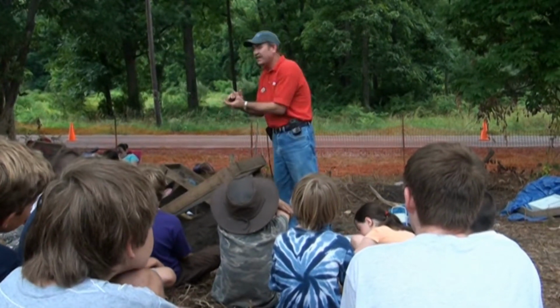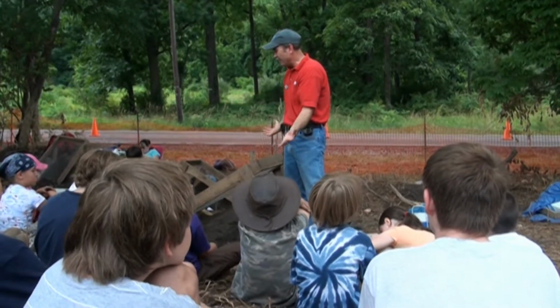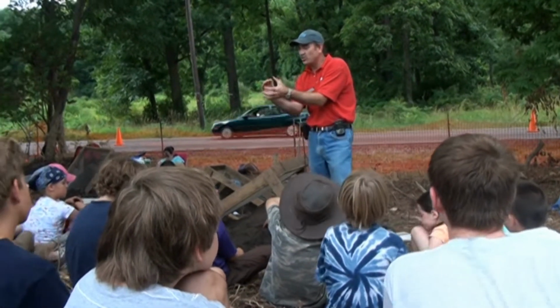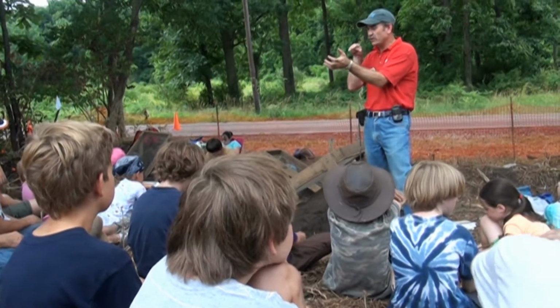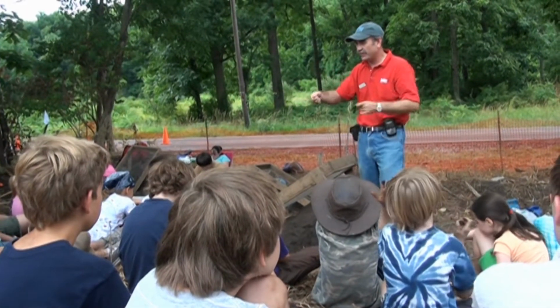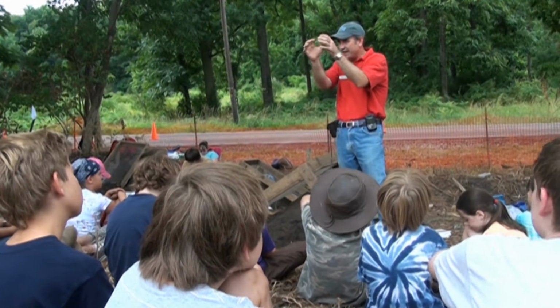And so you have good foundry sand in there, and you pack it all in there, and then you put your wooden cannonball in there, and you pack it all around it, and you make two different halves of this thing, and then you put that together, but the sand's holding its own, so you've got a void in there where that wooden thing was, that's now just an open space. And of course you have a little channel that's kind of drilled in there, and then you would take molten iron that's coming out of the furnace, okay, and pour it through the hole, and it would go in and fill that and make a cannonball.